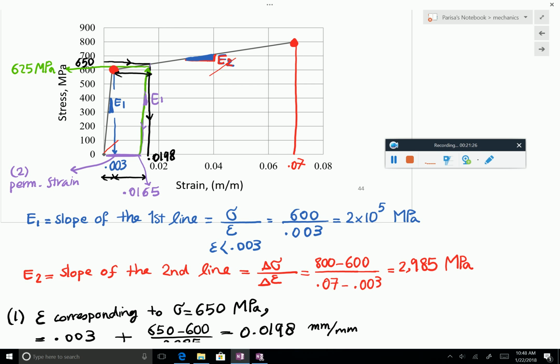So this same thing happens here. If you apply stress on the material, it hardens to a larger yield stress. So next time, the yield stress is not at 600, but it's at 650. It turns out that this is actually one way to increase the elastic range of metals. You can do that. You pre-stress it to have a larger elastic range. Very simple.